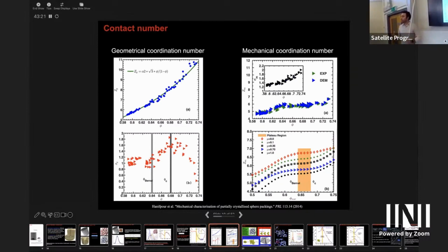Because we are able to recover bead diameters or radii at nanoscale, we can tell how much they are deformed experimentally. And we can basically find out how much force is going through each contact, okay? And because you have access to all these centers and radii, you can simply import them into any DEM software and let the structure relax, okay? And also measure the forces based on that, right? And so you get a really good agreement between experimental measurements and the DEM-based analysis. The good thing is that once you have access to the structure by DEM, you can play with other parameters.